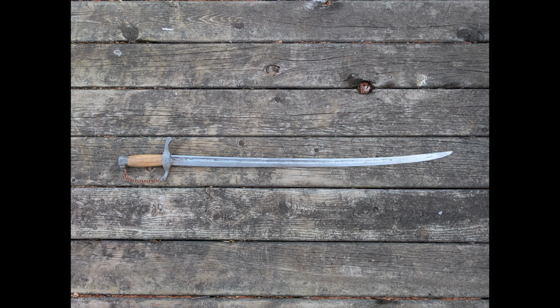So for alloy selection, we first considered going with something like a plain carbon steel like 1060 or a low alloy steel like 4340. But a key concern with this project was that the sword blade, being very long and thin, would be prone to warping during heat treatment, which you can fix afterwards, but it's just more difficult. So to avoid this, we decided to use a 17-4 precipitation hardening stainless steel, and the precipitation hardening